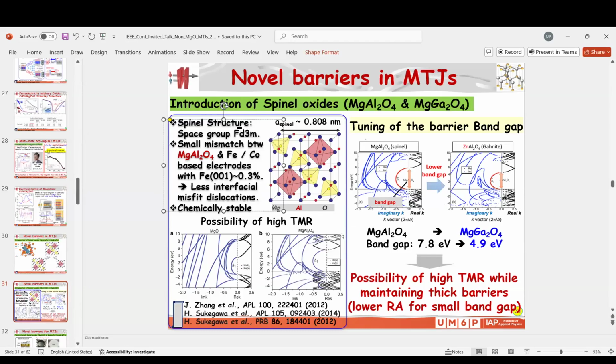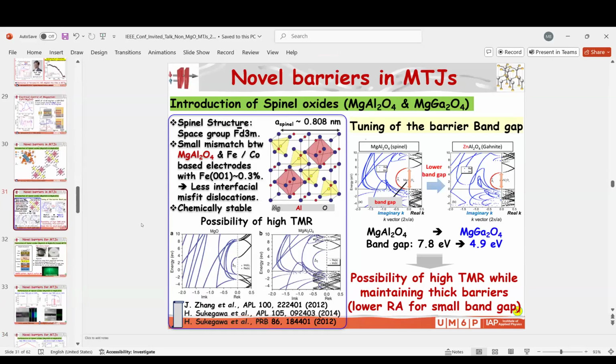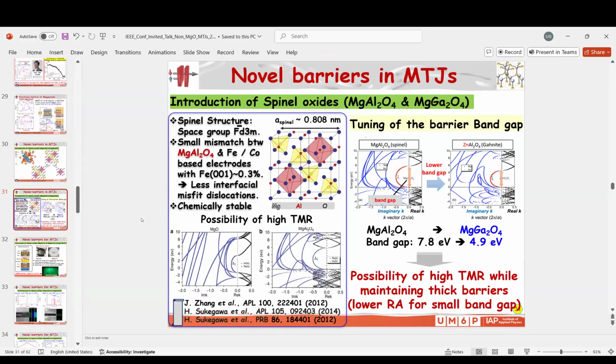In the beginning, we tried at NIMS to fabricate some good quality magnesium aluminum oxide, which is similar to MgO in terms of band gap. Then we shifted to magnesium gallium oxide, where the band gap is 4.9. Then to zinc aluminate, which has a lower band gap that I will show later. By lowering the band gap, of course, we expect to lower the RA.